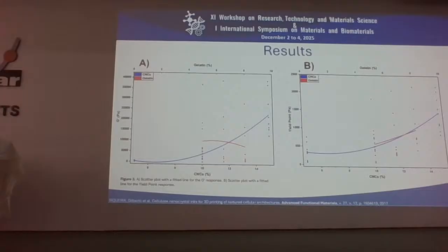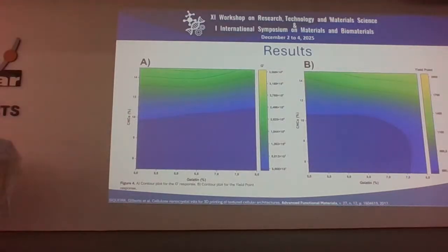Through the analysis, I found that cellulose crystals are primarily responsible for the rheological response, increasing both the elastic modulus and the yield point. And that's good, because if I want to increase the rheological response, I just need to add more nanocrystals. So I could discover how the nanocrystals interact with my hydrogel. I also found an interaction between gelatin and nanocrystals, indicated by the curvature of the contour plots. We can see this in figure 4, and it's more visible in the yield point response, as shown in figure 4b.